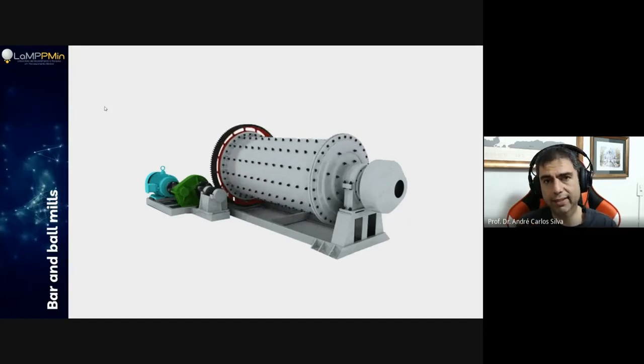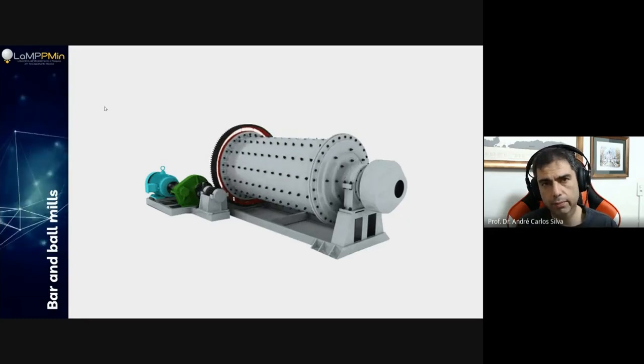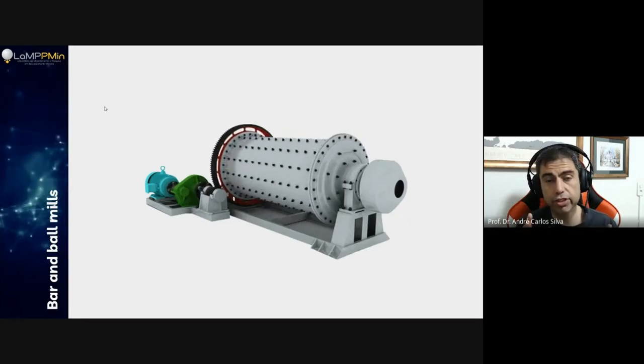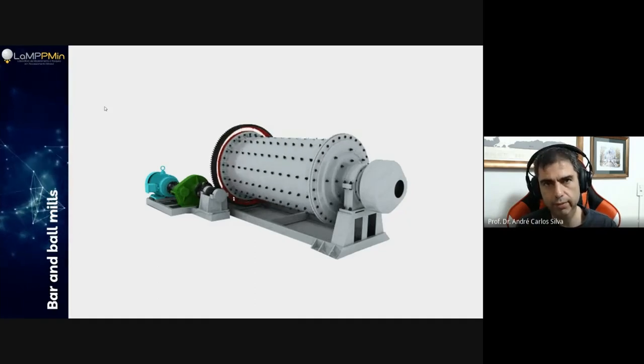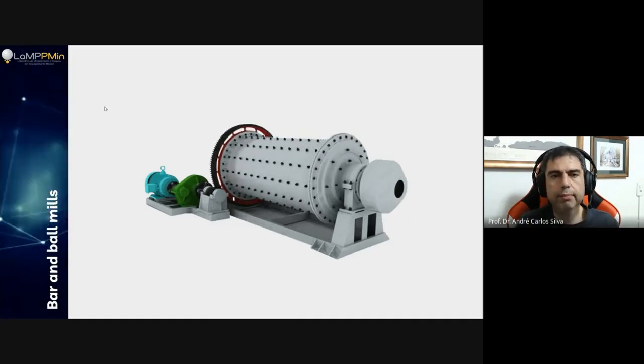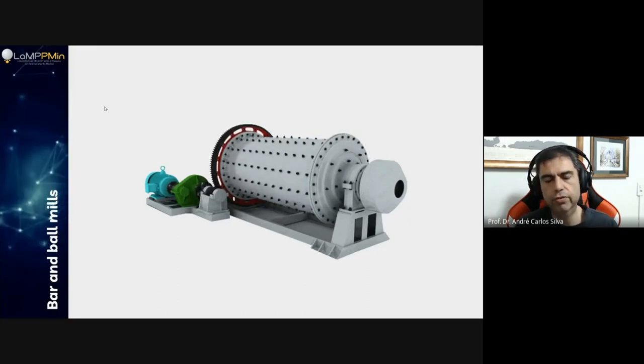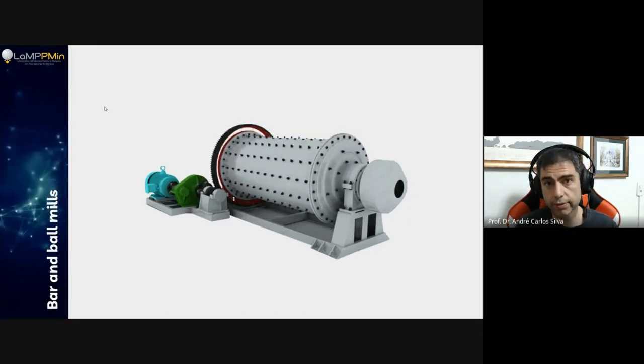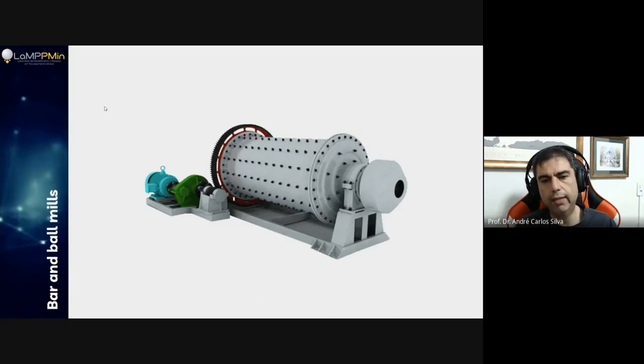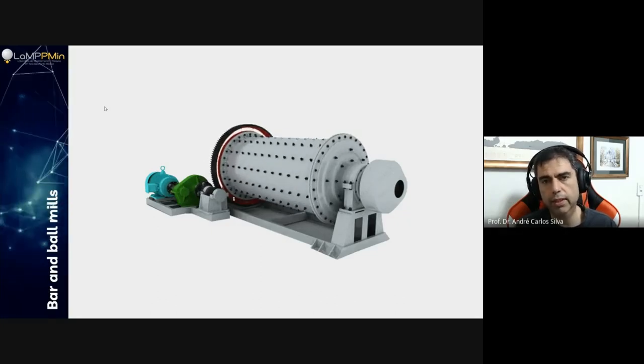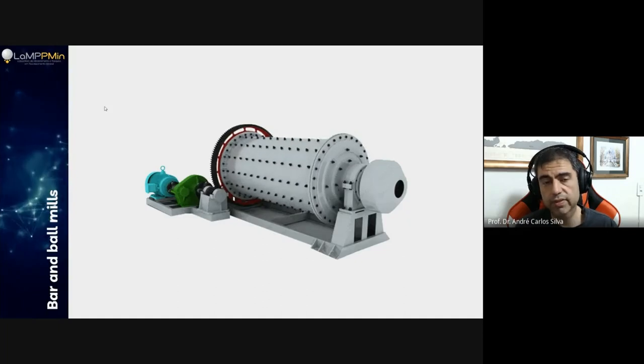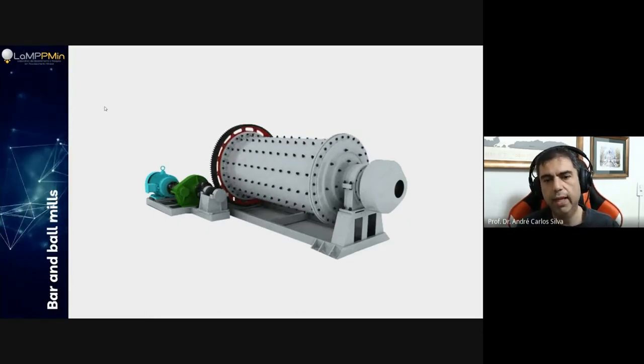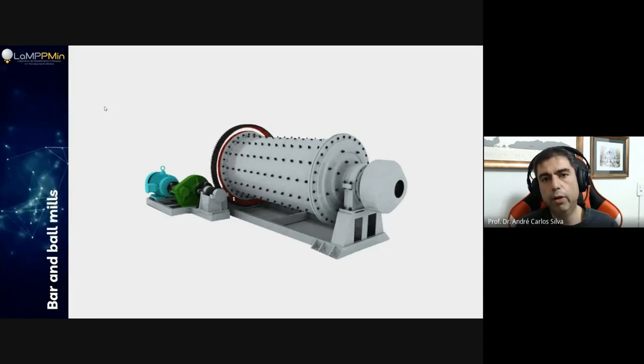If you take a look at a mill like this, it's going to be either a bar or a ball mill, okay? Normally, for this geometry, this would be a bar mill, okay? Why bar? Because you put bars, rods, inside of the mill. So another way to call this would be rod mill, okay? So bar mill or rod mill would be the same. And these rods are made of steel. Normally we can have something like chromium steel, and specific mass would be around 7.5 up to 8 grams per cubic centimeter. And the length of the bar is almost the length of the mill.